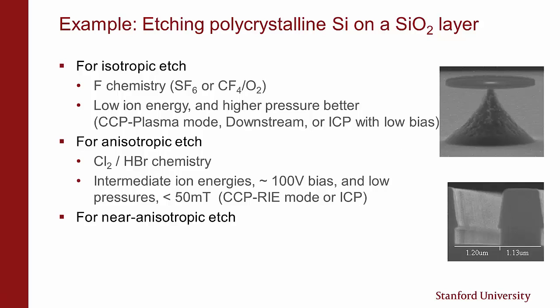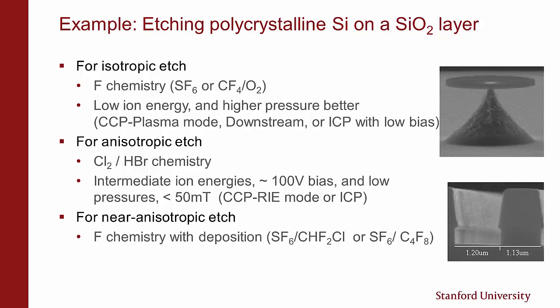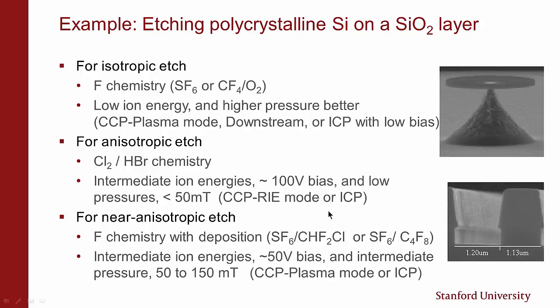For the near-anisotropic profile case, we again want to use fluorine chemistry but with inhibitive deposition. This can be SF6 with CHF2Cl, or SF6 with C4F8 — a combination of fluorine from the SF6 with deposition from the additive gas. In this case, we want intermediate energies — maybe around 50V bias — and intermediate pressure of 50 to 150 milliTorr. This could be CCP plasma mode or ICP, since ICP gives a wide range of energy possibilities.